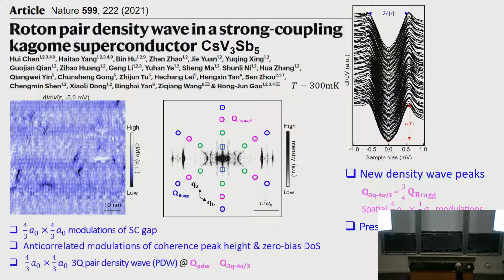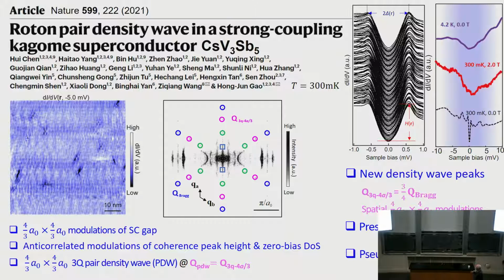And what are these? It turns out the superconducting gap, that is the distance between these peaks, shows a spatial modulation at this wave vector. The coherence peak height, that's this thing measured here, you look at its spatial distribution, that modulates with this wave vector. And also this zero bias conductance also modulates. So everything modulates with this 4a0 over 3 modulation. So we think, or they propose, this is actually a pair density wave state. And now explain why we call it a roton.